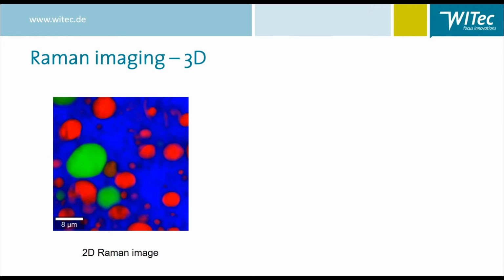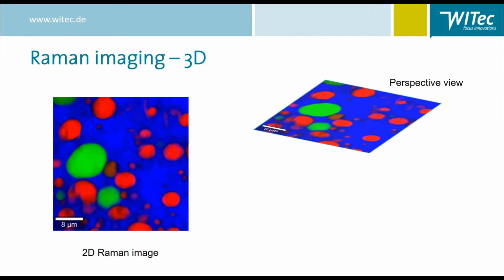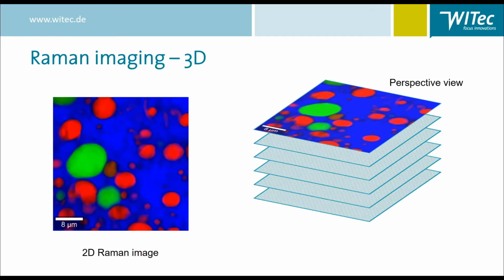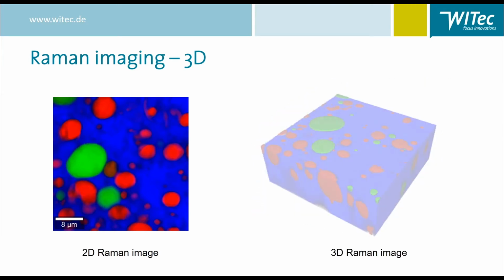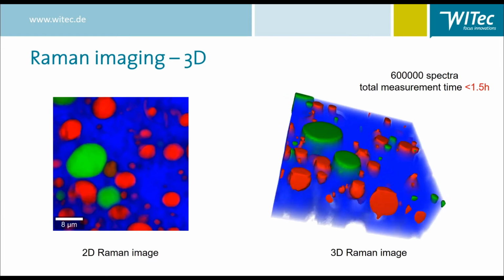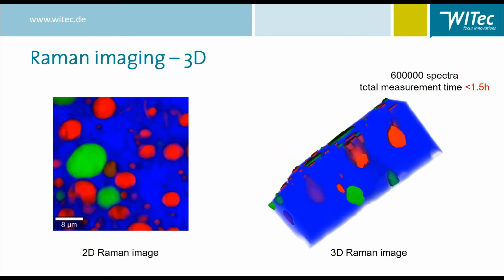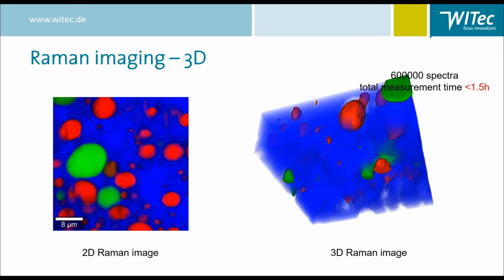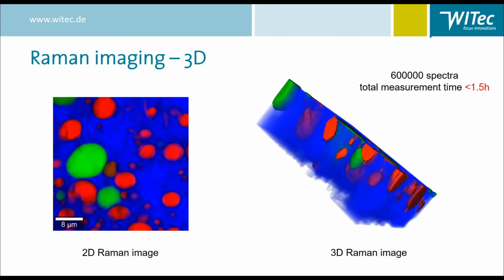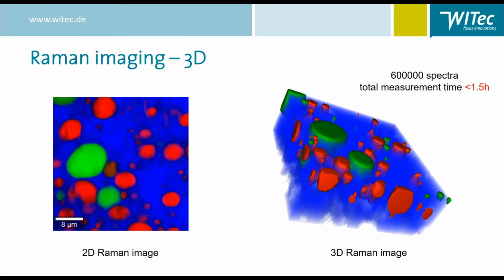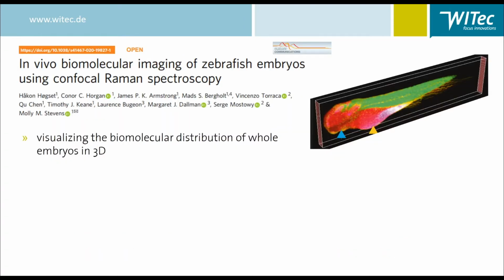To obtain a 3D Raman image, a stack of 2D images is measured, pixel by pixel, line by line, and layer by layer. And by doing so, we get the Raman information of a full 3D volume. The sample here is the hand cream with urea again. And this time we measured a full 3D Raman image. It consists of 600,000 Raman spectra. An integration time of 5 milliseconds per spectrum was used, leading to a total data acquisition time of less than 1.5 hours. And as the group of Molly Stevens demonstrated, this is even possible in vivo.